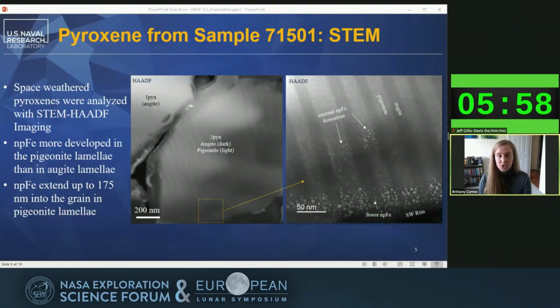Moving the sample then to our STEM instrument, so now we're imaging with a focused probe. We acquired high-angle annular dark field, or HAADF, images. HAADF is a Z-contrast imaging technique that helps us better examine the space-weathered rim, because here the more iron-rich phases are going to show up brighter. So now we're going to flip our contrast from the previous image.